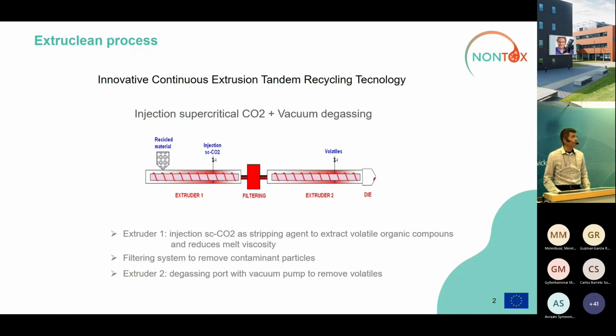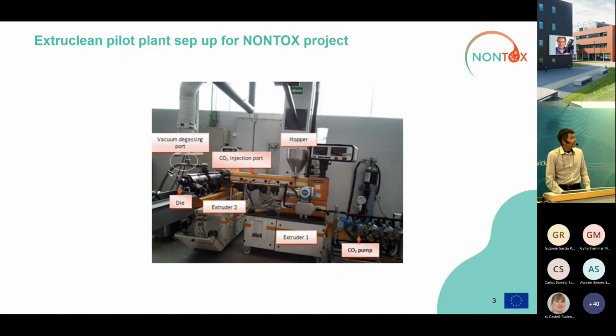This is a schematic view of our process, as we call it the tandem single screw extrusion system, in which in the first extruder we inject gas CO2 in supercritical conditions as a stripping agent to extract volatile organic compounds, and also helps to reduce melt viscosity, providing a more gentle processing in order to avoid thermal stress and degradation. Also, it is possible to place a filtering system between the two extruders in order to remove contaminant particles. And in the second extruder, we provide extended residence time in order to solubilize these volatile and contaminant substances. And at the end, the degassing port allows the removal of volatile substances. And this is how this Extruclean tandem recycling technology looks like as we set up in AIMPLAS pilot plant facilities.